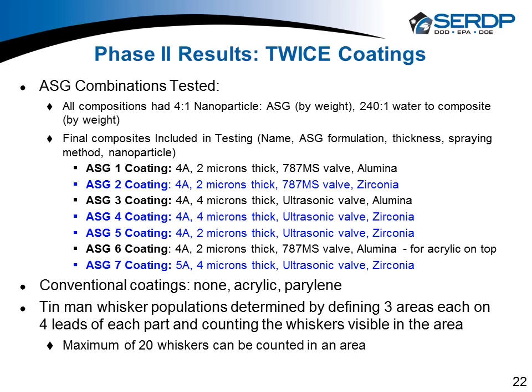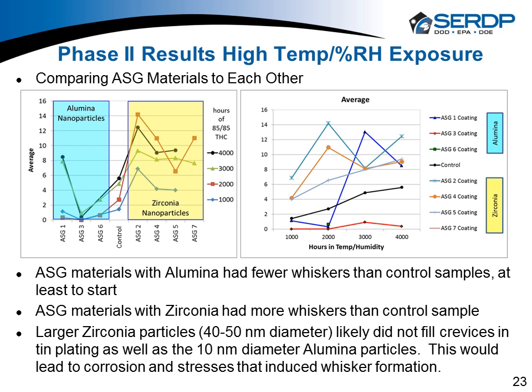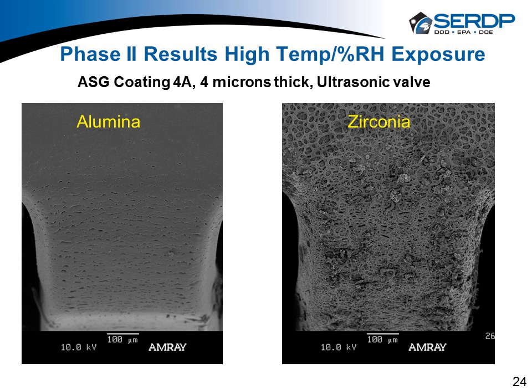And so at phase two, we kind of switched gears a little bit. We kept our phase one valve, but we looked at a new application technology, and then we also looked at a new particle. Of course, in the test, we kept no coatings for control. We did acrylic, we did Parylene, we did the liquid glass, and we did the same type of measurement, whisker length and density that I discussed in phase one. So I'm going to skip ahead one slide, I'm going to come back. We're going to go to slide 24.